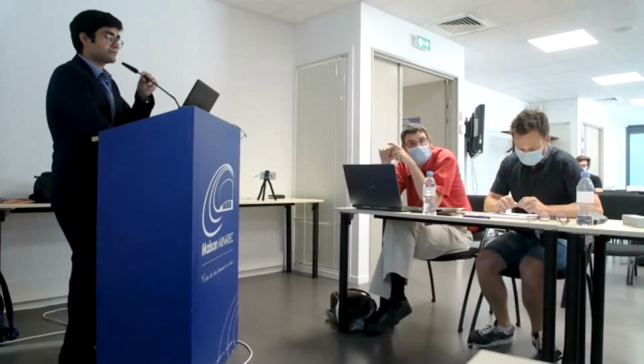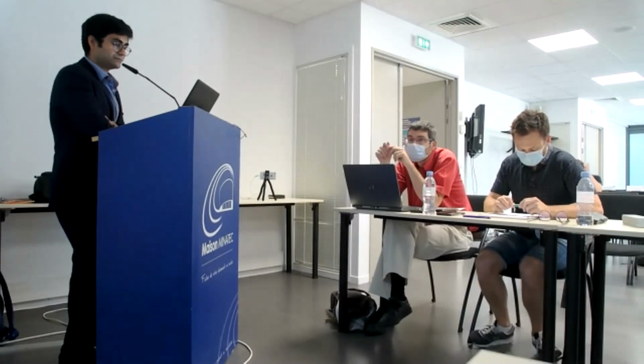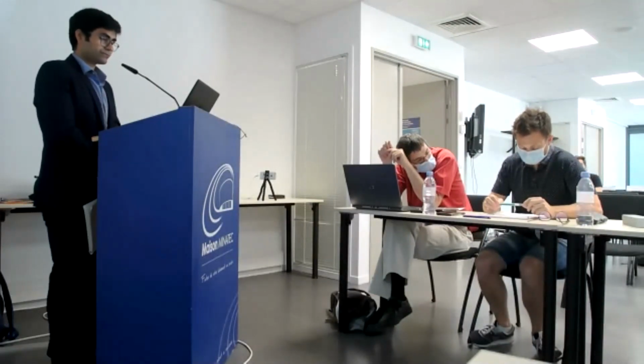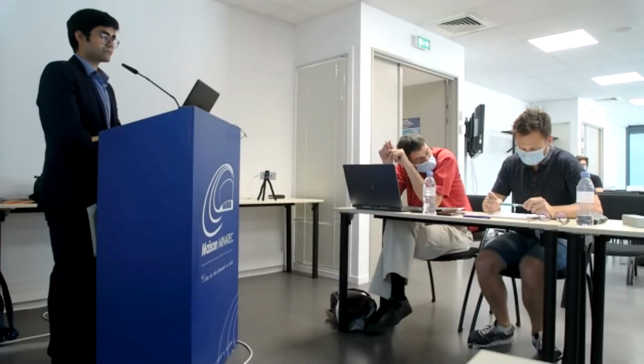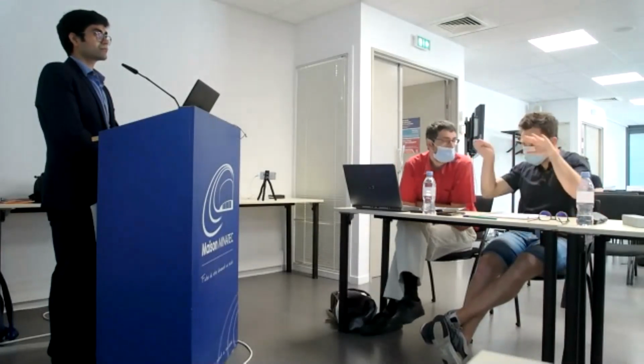The second point would be the effect of strain relaxation. When you said that between traditional solidification and L-PBF you see a huge difference in pressure drop, I was wondering, if it was a real physical phenomenon, the cavitation in the liquid should be almost instantaneous, and it should not depend so much on time, right? However, the surrounding solid, if you leave a lot of time, might relax some stresses. So do you think there is a big difference in strain relaxation between traditional solidification and fast solidification conditions? And could this explain some of the difference you see in the pressure drop?